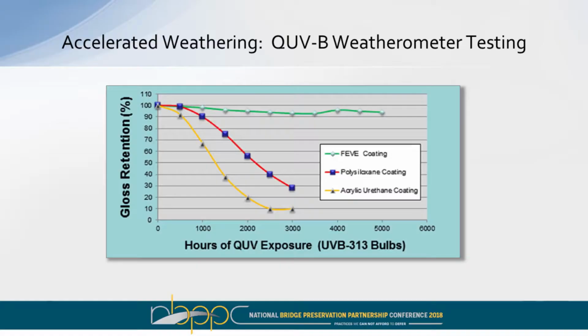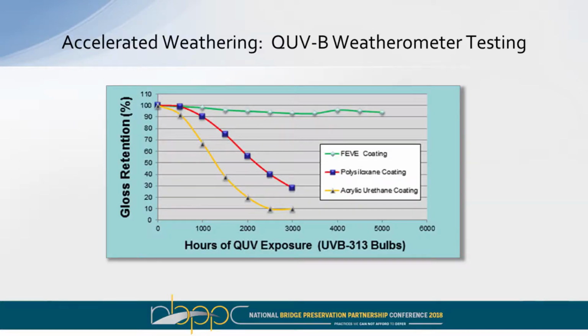This is a typical chart that we see for accelerated weathering. This one is called QUV-B. The coatings are exposed to one wavelength of light at 313 nanometers. And we use gloss retention as a proxy for performance. So the higher the gloss retention, that is, the flatter that line is, the better the gloss retention and the better the durability of the coating. And you can see they've compared this to a standard polyurethane.